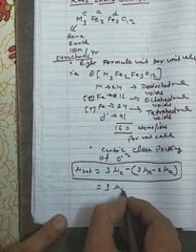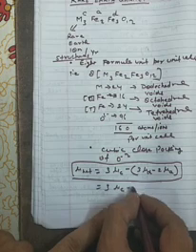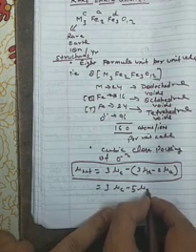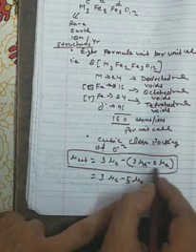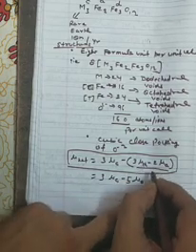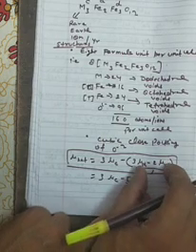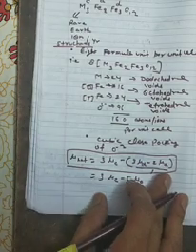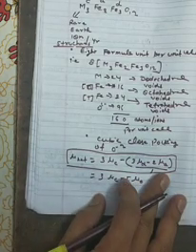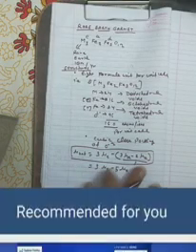And from this moment, if we subtract the difference, finally what we get is 3 mu A minus 5 mu B. Each iron in 3 plus state has 5 unpaired electron spin vectors, each corresponding to one Bohr magneton, so there will be 5 mu b.